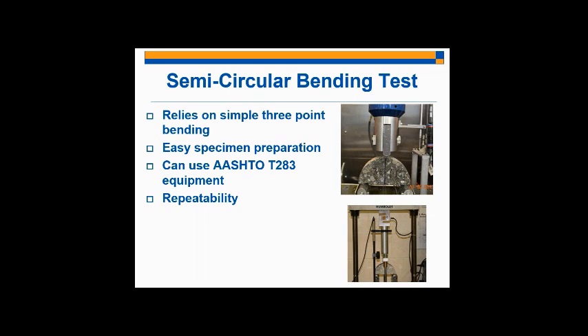And the most important thing is that we can test these specimens under a very simple pneumatic load frame. You can see in the picture at the bottom right of the slide the Humboldt load frame. This is actually the load frame used for the TSR test. We've modified the fixture for the standard TSR test. It's a very simple, cost-effective modification, and you can run the test on the Humboldt load frame at a very cheap cost. This is the final objective of the project, to be able to deliver a test that runs on the Humboldt load frame properly.